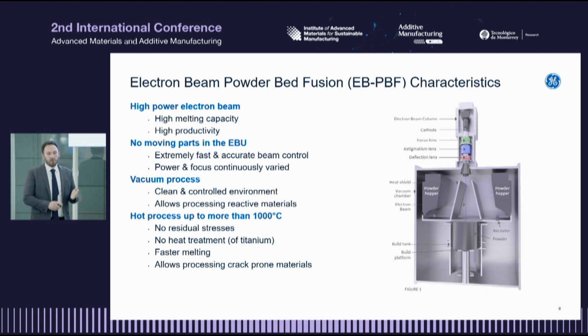There are no moving parts in the beam column for EBM. Because we don't have photons to move around, you're classically moving those with lasers. I'm using 3 electromagnetic lenses to move those from point A to point B. This beam moves at 8,000 meters per second to get from one location to another. We're also processing in an inert atmosphere that is not gas-based, it's vacuum. We pump a hard vacuum. You end up losing energy and you get backscatter from electrons running into air particles, so we remove those from the equation.